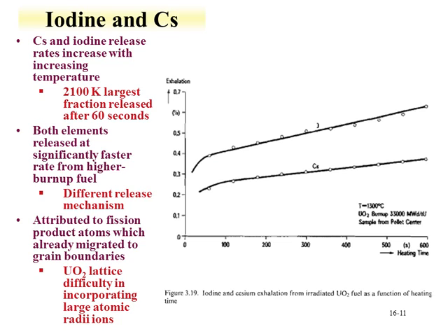Some of this behavior, also at higher burnup, is attributed to the fission products migrating towards the grain boundaries. We already discussed that the fission products themselves travel a distance on the equivalent of a fuel grain boundary, so they don't have to release themselves from the matrix of the fuel. They just migrate from the grain boundaries. Also, depending upon the fission products that are produced, the UO2 lattice may not be suitable for solubilizing larger atomic radii ions, so we could get different phase formation in the fuel.